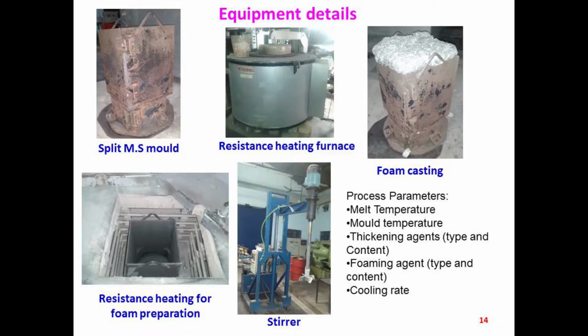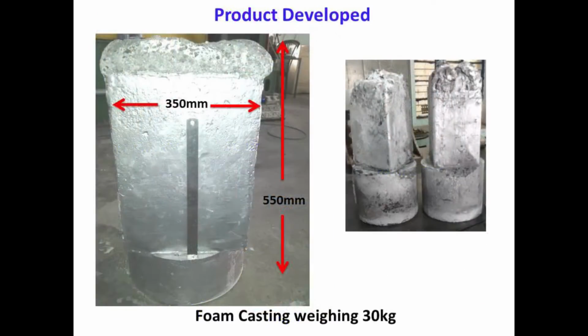Through this foaming crucible we can make 30 kg of foam at a time. So in a single crucible we can make 30 kg of foam. If we go through the whole day, we can make 250 kg of foam in a day in our laboratory. And this is the casting size, and from there we can slice the foam into different thicknesses.